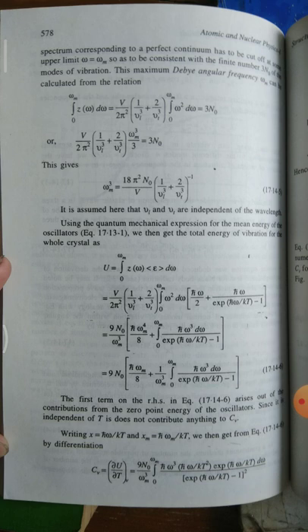Okay, it is 9N₀, and the ω_m³ and ω⁴ terms cancel, giving ħω_m/8 + 1/ω_m³ integration 0 to ω_m of ħω³ dω/(exp(ħω/kT) − 1). The first term on the right-hand side arises out of the contribution from the zero point energy of the oscillators. Since it is independent of T, it does not contribute anything to C_V. So U = 9N₀ ħω_m/8 + 1/ω_m³ integration 0 to ω_m of ħω³ dω/(exp(ħω/kT) − 1).